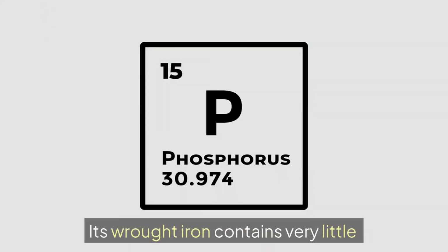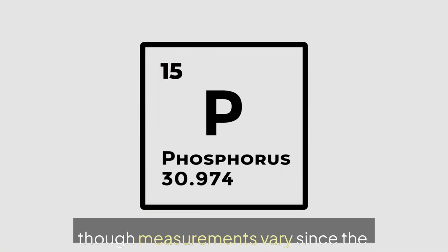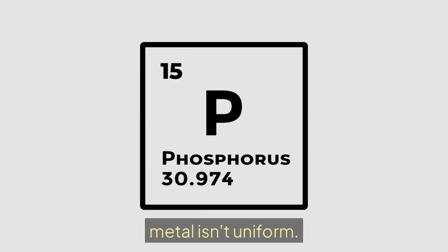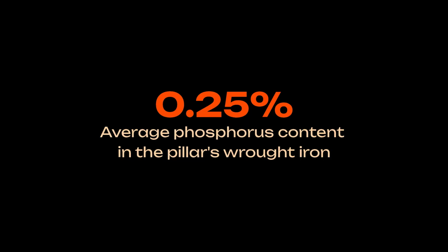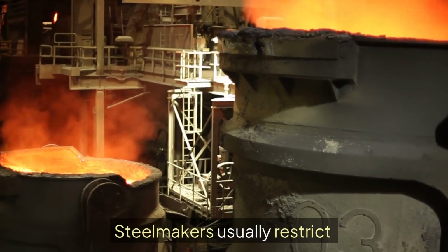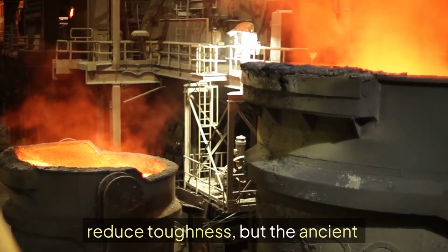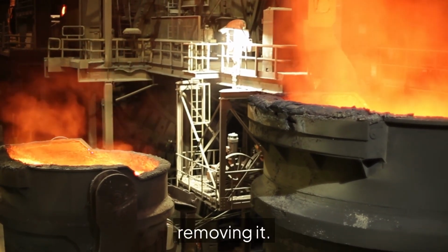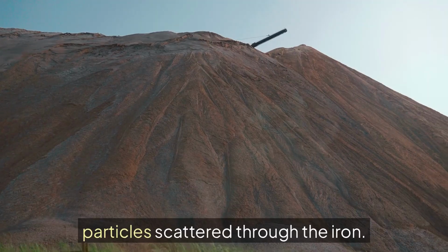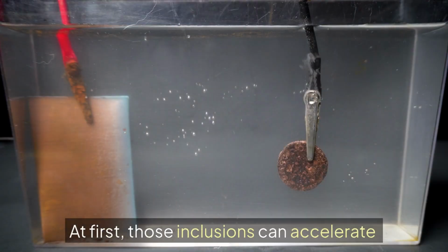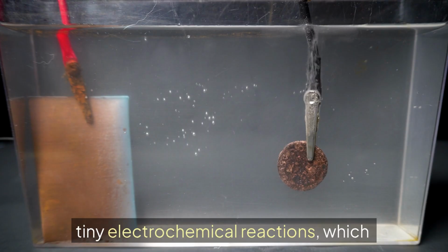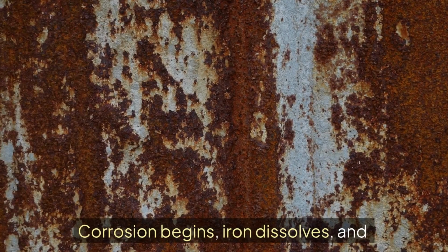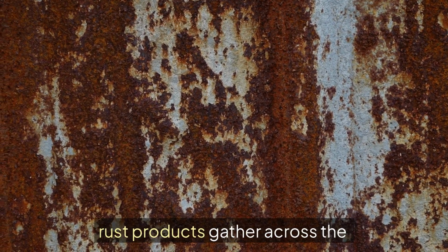Its wrought iron contains very little carbon, but unusually high phosphorus, though measurements vary since the metal isn't uniform. Reported phosphorus values range roughly from 0.11 to 0.48%, with an often cited average around 0.25%, and many modern structural steels contain far less. Steelmakers usually restrict phosphorus because too much can reduce toughness, but the ancient smelting route didn't prioritize removing it. Its solid-state process also left slag particles scattered through the iron. At first, those inclusions can accelerate tiny electrochemical reactions, which sounds disastrous. Corrosion begins, iron dissolves, and rust products gather across the surface.